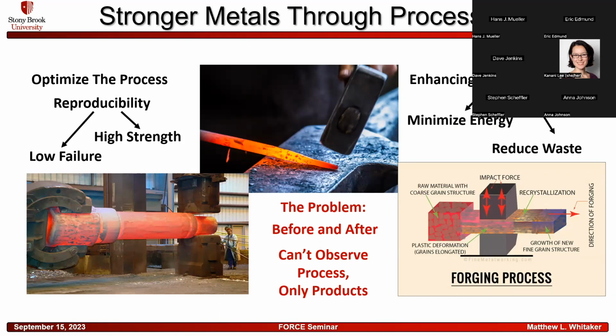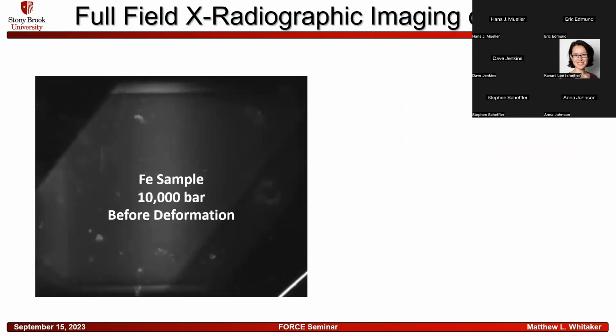We can only see the products. And that's where the synchrotron comes in, in particular the MAX PD end station that we have at NSLS2. So we can take the sample to, in this instance, 10,000 bars of pressure, 1 GPa, and we can collect some full field X-radiographic imaging of the iron sample.